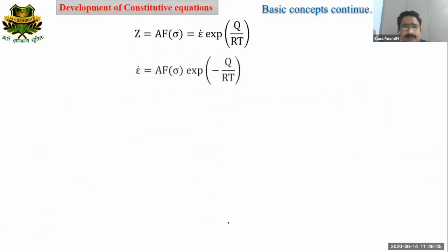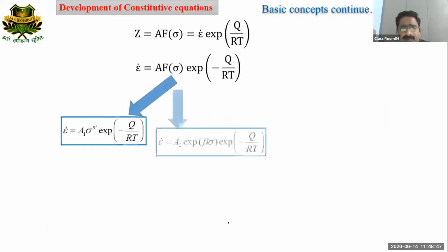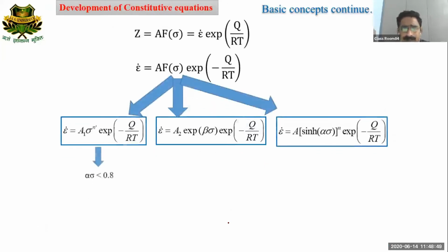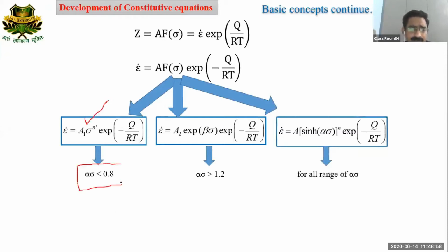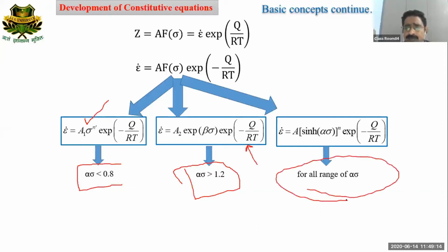So here I'm just explaining how we can calculate the parameters. In this particular slide, you can see that this particular equation is useful when the product of flow stress multiplied by alpha is less than 0.8. And when the value is greater than 1.2, then this exponential expression will be used, but for the whole range, we can use this sine hyperbolic equation.